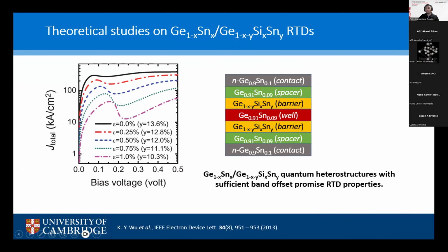Okay, so just a background story. Almost a decade ago, a group of physicists from Taiwan predicted the occurrence of resonant tunneling in this kind of germanium tin heterostructure. In their case, they used a germanium tin spacer layer, and they varied the strain in the barrier by varying the silicon content. Theoretically, as you can see, when they induced 1% tensile strain, they obtained quite a large peak to valley ratio in here. However, no one had successfully demonstrated resonant tunneling at that time in experiment because of the experimental challenges to realize germanium silicon tin with quite flat interfaces and good quality.